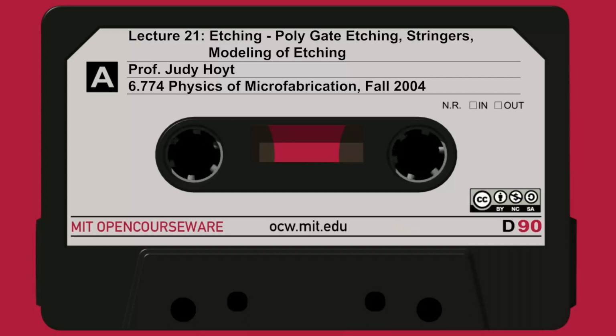So as a result, once I've cleared the flats, I still have this little notch of material that's unetched, that's sitting there, because my etch only etches vertically. If the etch had etched sideways, then you wouldn't have to worry about that notch. So an isotropic etch doesn't tend to give you stringers, or stringer formation is not such a big deal, but if it's anisotropic, it is. So what we do is you continue in step C with an over etch, you continue to beat down on this and introduce an extra 50% of an over etch to get rid of the stringers.